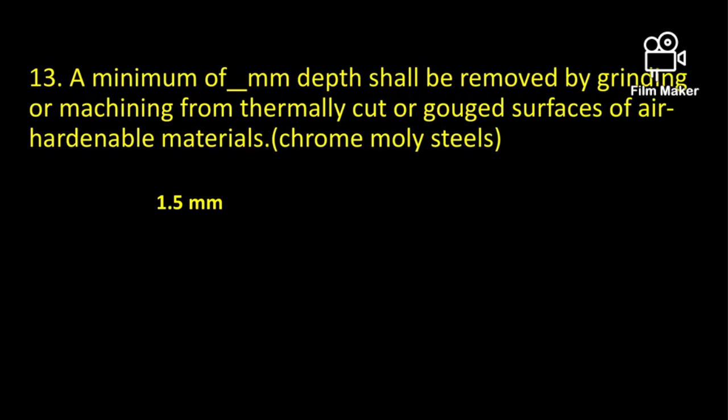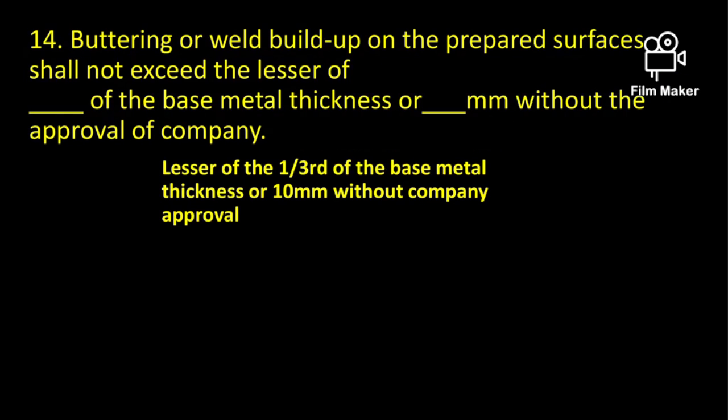A minimum depth shall be removed by grinding or machining from thermally cut or gouged surfaces of air hardenable materials, i.e., chrome moly steels. That minimum depth is 1.5 mm.